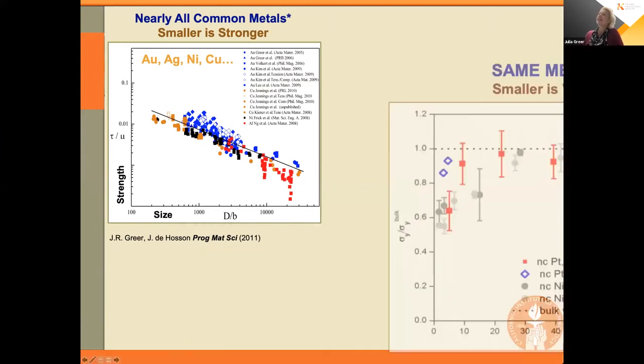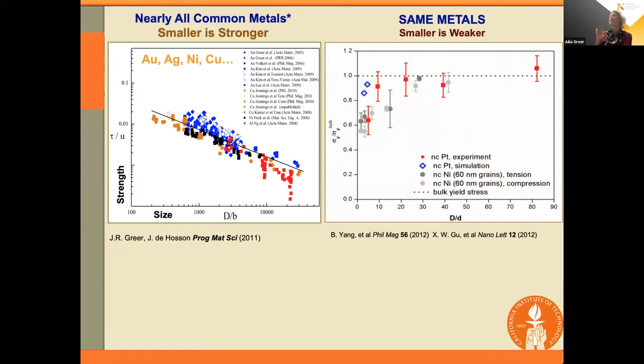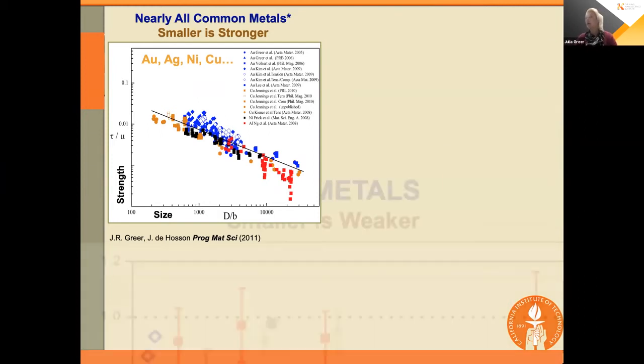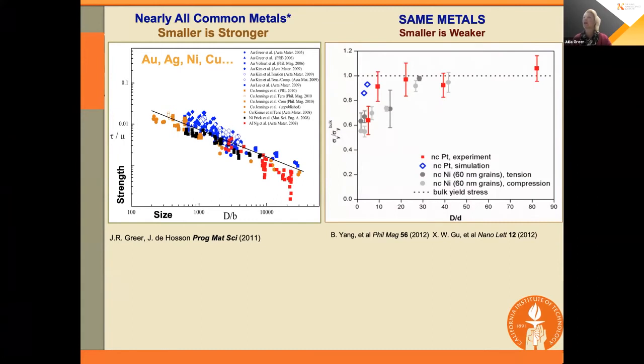Now take exactly the same metals but deposit them using different techniques, for example, chemical vapor deposition or sputtering. And the microstructure, the atomic level microstructure, is now nanocrystalline. And what you can see is that this effect is reversed. Smaller is now weaker, not stronger like it was in the case of single crystalline metals. This is a more modest size effect because it's not on a log plot.